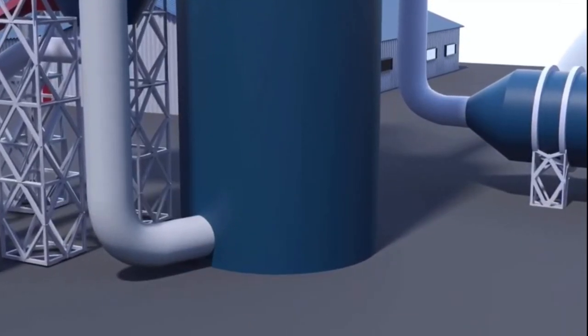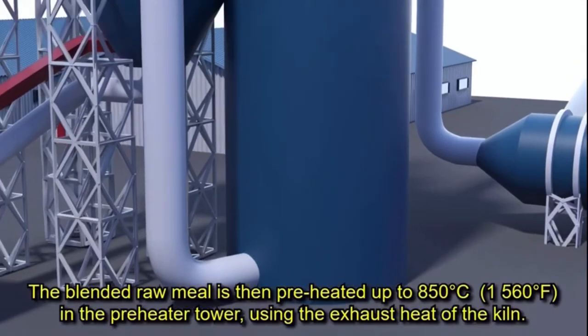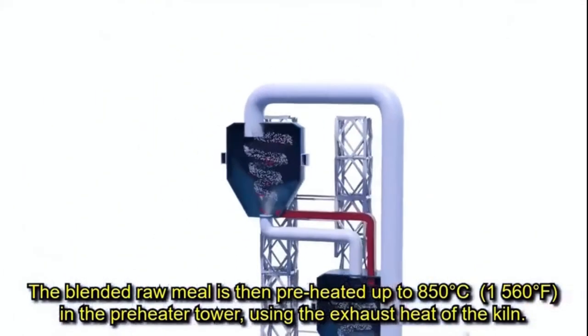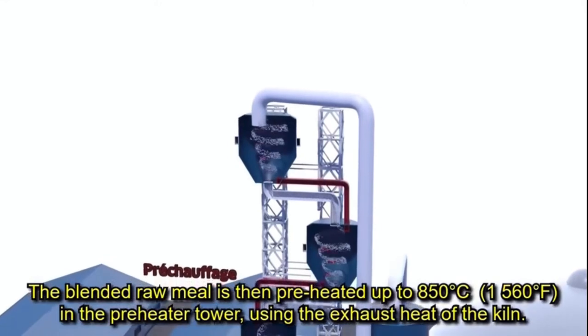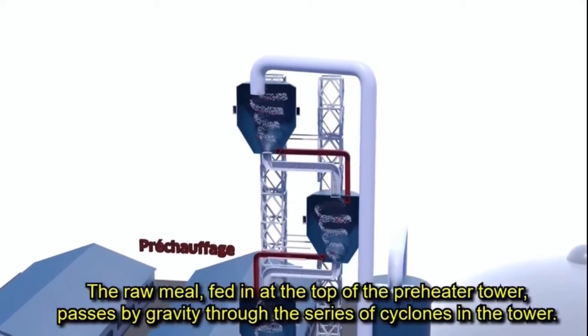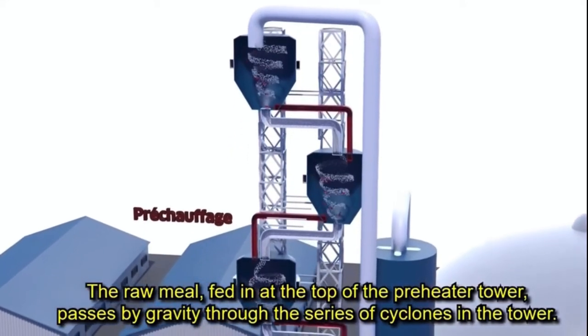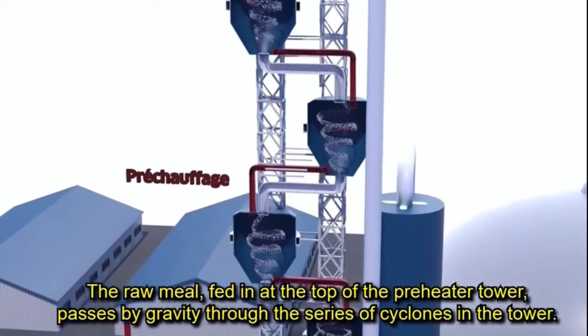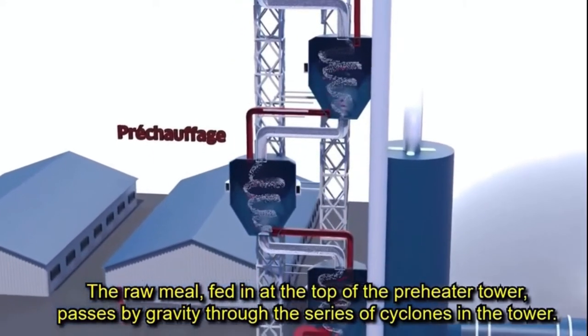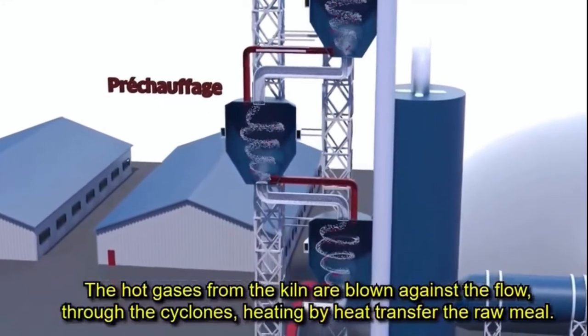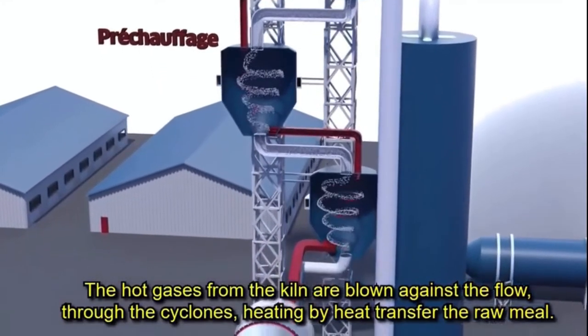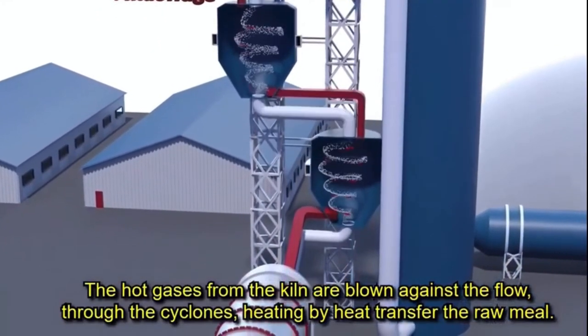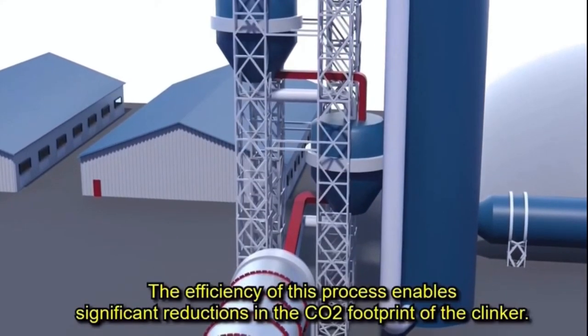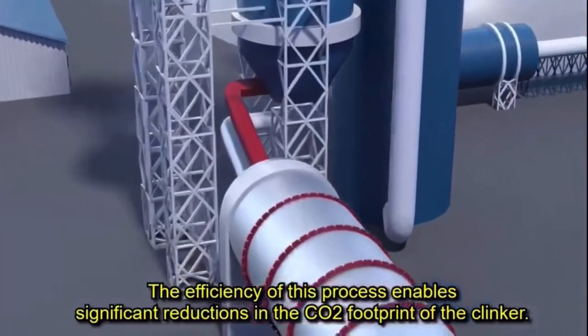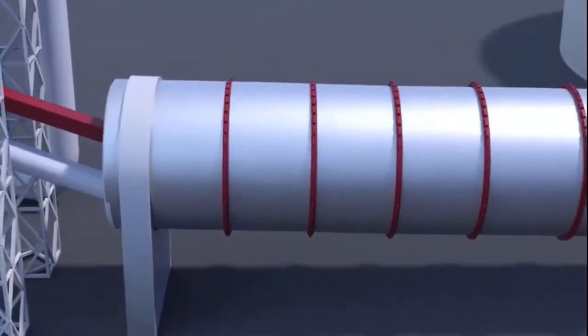Preheater. The blended raw meal is then preheated up to 850 centigrade in the preheater tower using the exhaust heat of the kiln. The raw meal fed in at the top of the preheater tower passes by gravity through a series of cyclones in the tower. The hot gases from the kiln are blown against the flow through the cyclones, heating the raw meal by heat transfer. The efficiency of this process enables significant reduction of the CO2 footprint of the clinker.